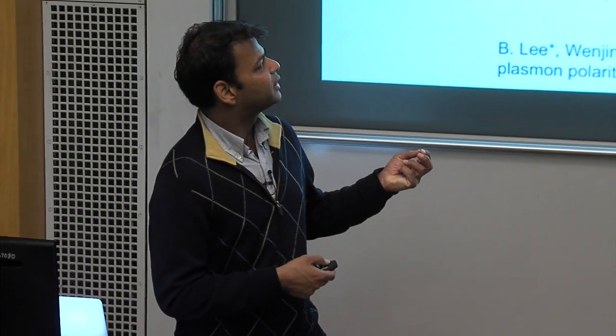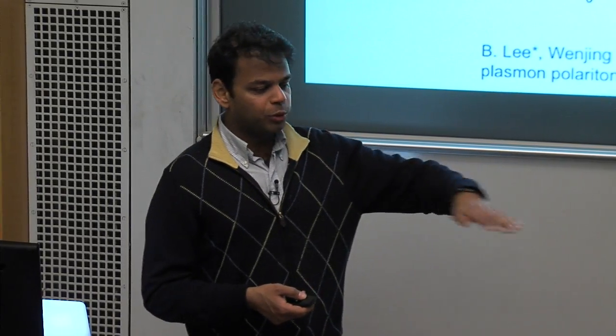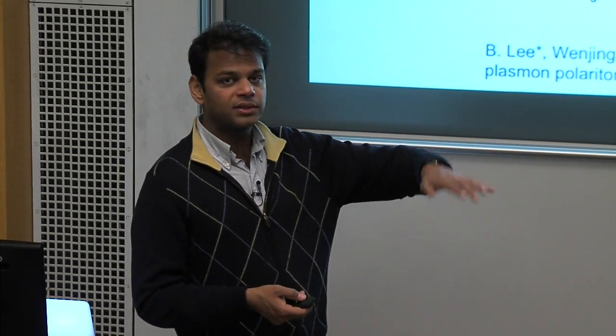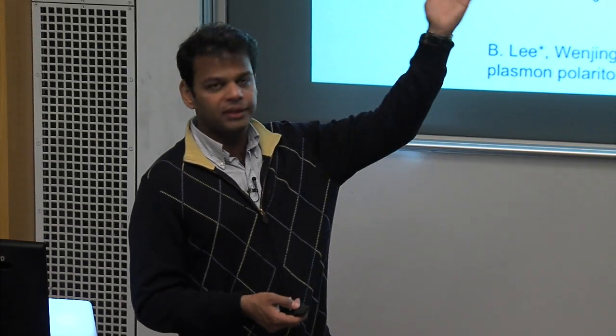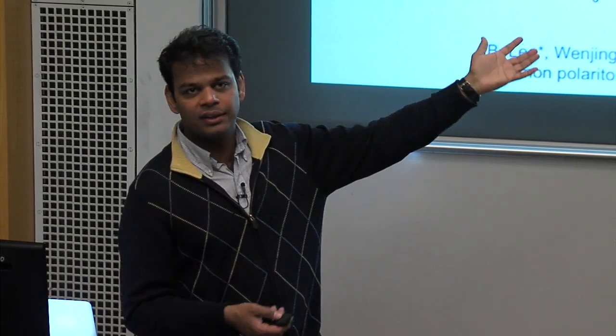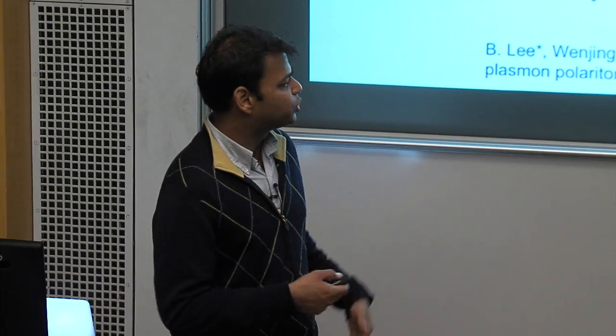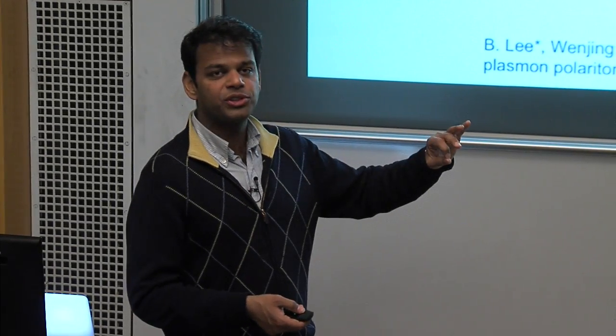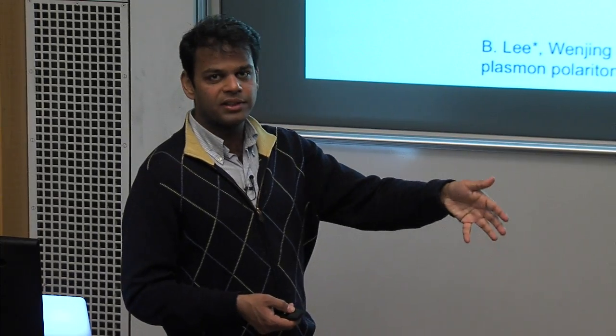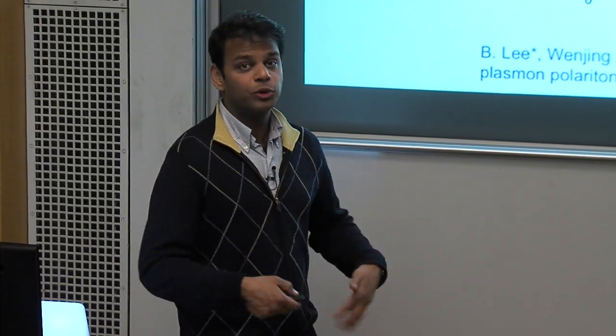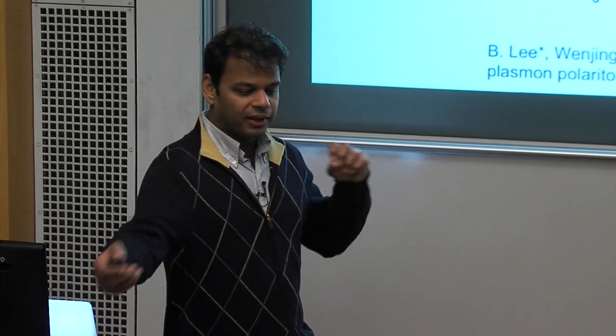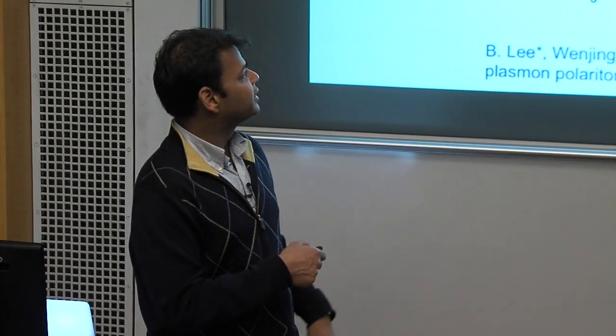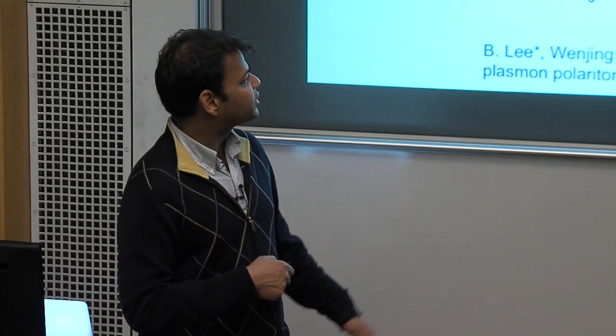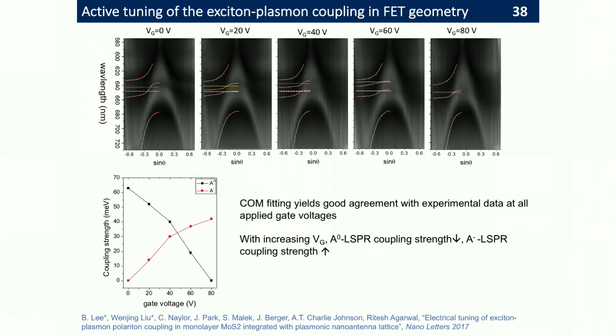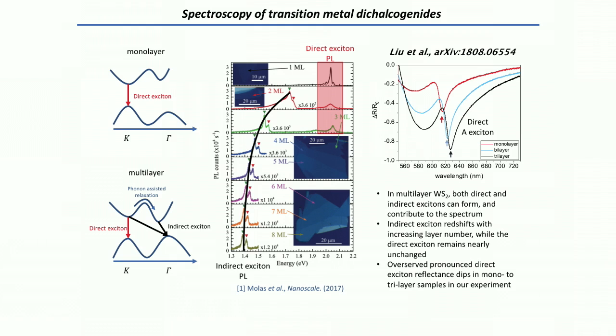And another very interesting thing here is when you gate a system, you basically inject carriers at the interface of your gate oxide and the semiconductor. But the other 99.9% of the material does not experience those charges that you inject. But since this material is only a single sheet of material, all the carriers that you put into the system are forced to interact. And because the screening is weak, they can interact over longer distances. And hence, at reasonable carrier injection strengths, you can get this very strong behavior. Okay? So this is one attribute of this reduced carrier screening.